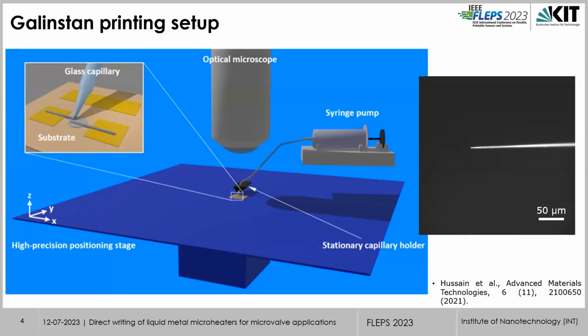Here we use glass capillaries. The typical opening is around 3 to 5 micrometers, and then we connect it with the plastic hose to a syringe pump. We put liquid metal galinstan into the syringe, and we push it with the pump, and the liquid metal comes out of the tip of the glass capillary. The stage can go in X, Y, and Z directions, and with that, with the predefined pattern, we can print things, and everything can be monitored with the optical microscope.